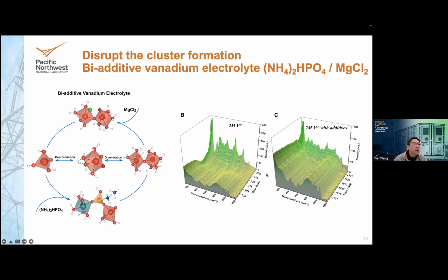from precipitating. This is the in situ NMR, which shows that those peaks are the indication of the precipitation of vanadium 5 solid, either V2O5 or V2O3. You can see that in 2 molar without the additive, those peaks appear much earlier, around 250 to 270 minutes. But after you add the additive, those peaks show up much later, close to 18,000 or 19,000 minutes. So this is also an effective way to stabilize the electrolyte.